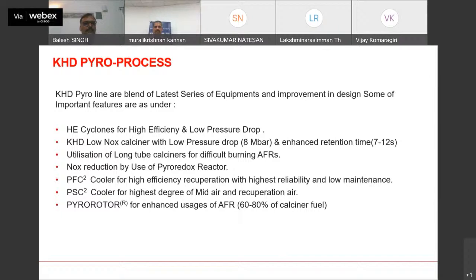Then next comes the KHD low NOx calciner with low pressure drop. Earlier we were facing some higher pressure drops in previous designs, but with time and development in the technology, it is now optimized up to 7 to 8 mbar, and it has also enhanced retention time, say 7 to 12 seconds in the calciner. Utilization of long tube calciner for difficult burning of AFRs. NOx reduction by use of pyroredox reactor. So these are all the new developments.